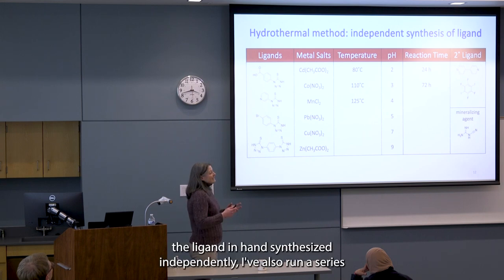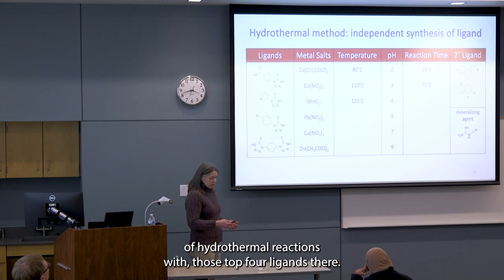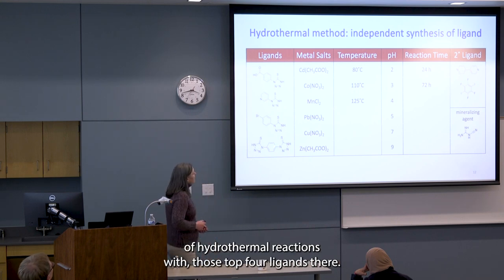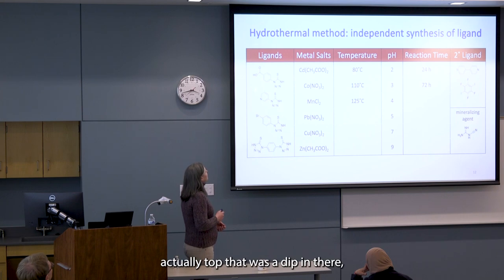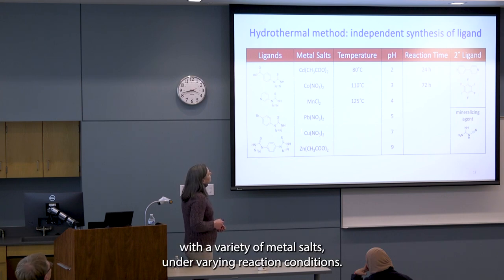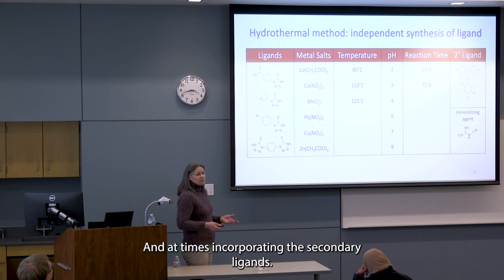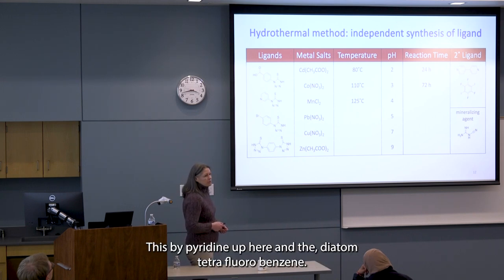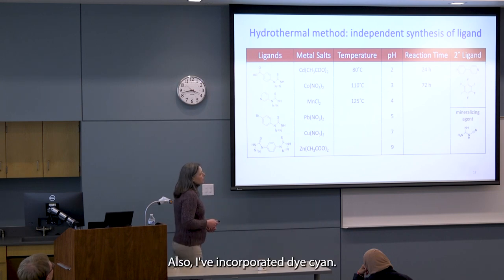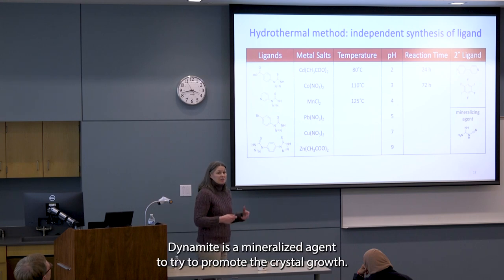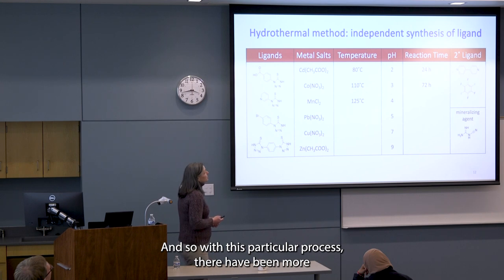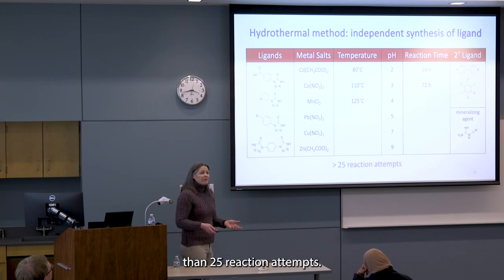So with the ligands in hand, synthesized independently, I've also run a series of hydrothermal reactions with those top four ligands, not the fifth one. With a variety of metal salts, under varying reaction conditions, and at times incorporating secondary ligands, this bipyridine up here and the diiodotetrafluorobenzene. Also, I've incorporated dicyandiamide as a mineralizing agent to try to promote the crystal growth. And so with this particular process, there have been more than 25 reaction attempts.